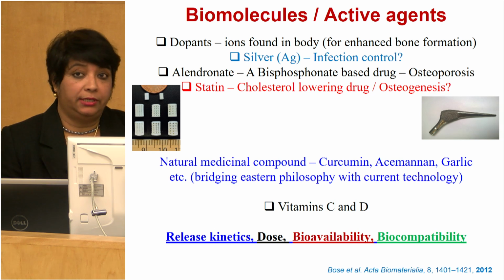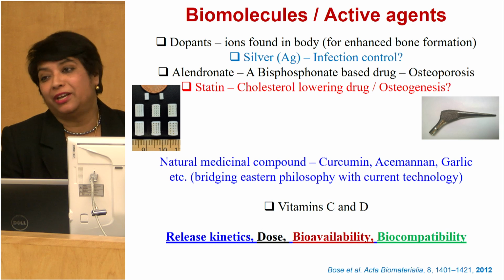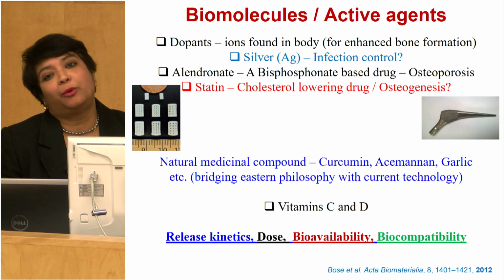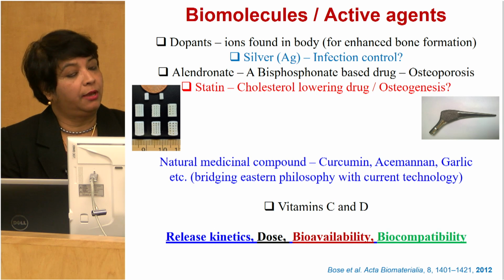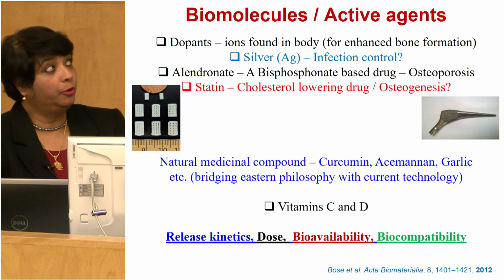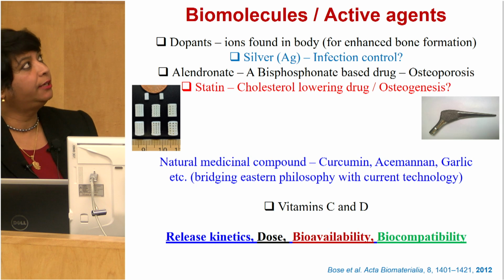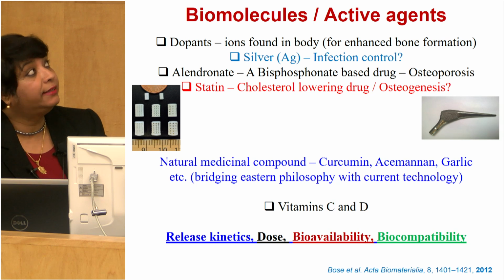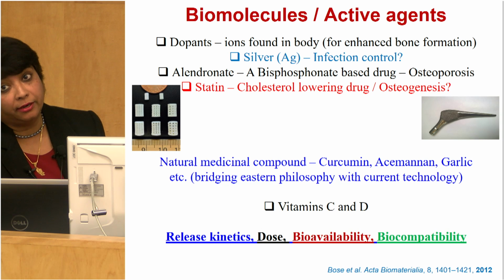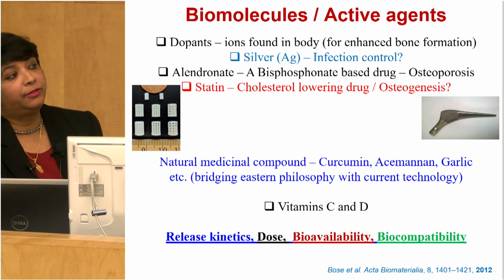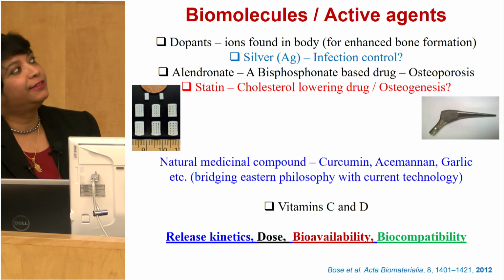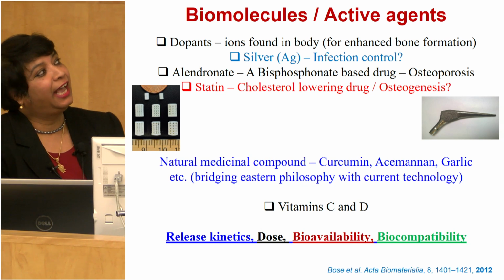Clinical science already shows that after taking bisphosphonate drugs for 4 to 5 years, our bone actually becomes more fragile, because the way it works is it stops osteoclast or bone eating cell activity. So it kills the bone remodeling cycle. So not many physicians are very enthusiastic about prescribing that alendronate drug anymore or bisphosphonate based. There are many forms of bisphosphonate, alendronate, zoledronate. For statin, it is a cholesterol lowering drug like lovastatin, simvastatin. However, recent research has shown that it can have some effect on bone growth. So we looked at some of these drugs for osteogenesis and we saw some nice results.